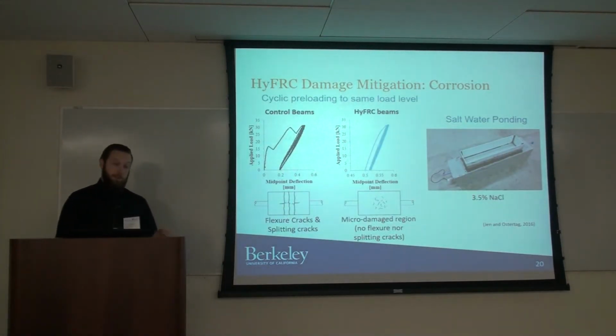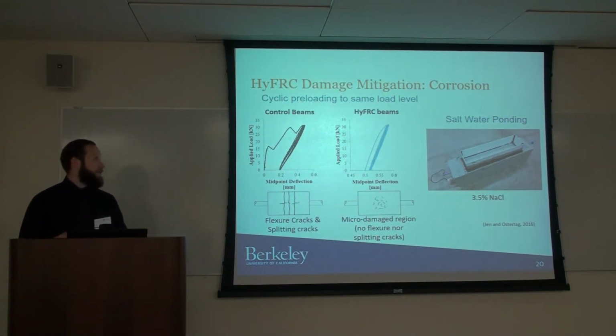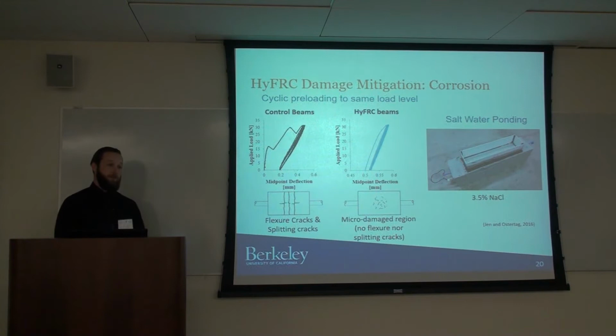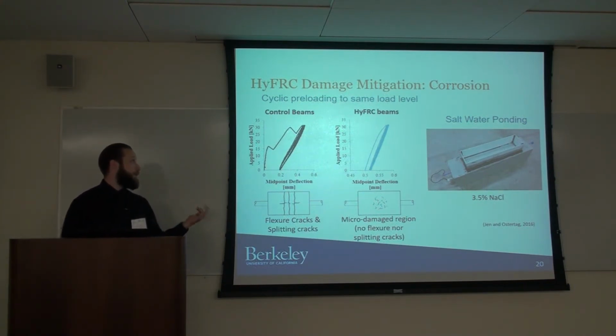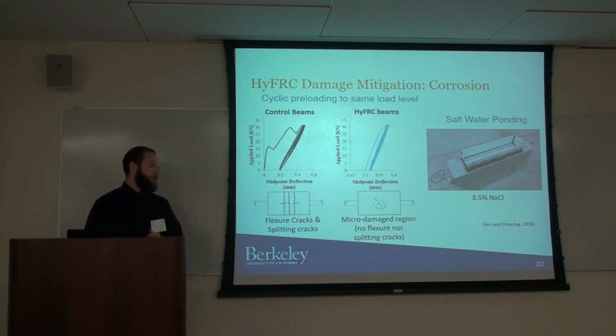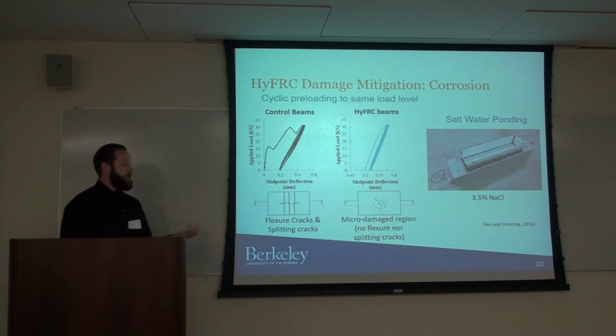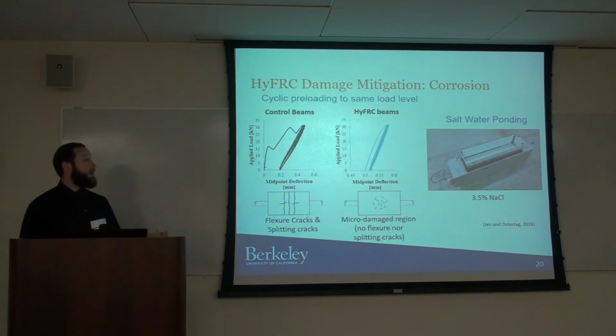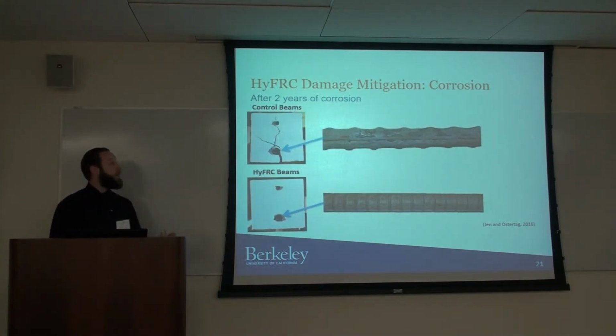Additionally, in addition to the seismic behavior of this material, it has also separately been shown to improve the corrosion behavior, both in the initiation period as well as the propagation period. And this comes down to crack control. So we tested fiber reinforced concrete beams compared with a control specimen, and due to this diffuse microcracking under a given loading, we were able to decrease cracking in the specimens, which maintains the concrete cover and prevents chloride diffusion under an extended period of saltwater ponding. So these specimens, after preloading, were ponded with saltwater for 2 years, and you can see the behavior.